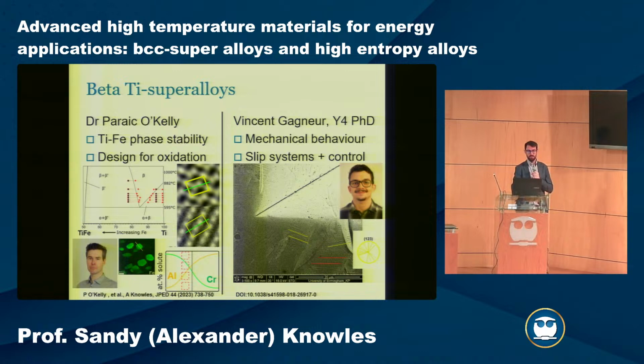We then went into more detail, so these are transmission electron microscopy images, where you can see the columns of atoms and how they're arranged. And we tried to use this as well as then adding in additional elements like aluminium and chromium in order to improve oxidation resistance. So this was one thing with Paraic. With Vincent, we then had a project where we were particularly interested in the mechanical behavior of these systems and looking at slip systems. So I'll talk about both of these in turn.